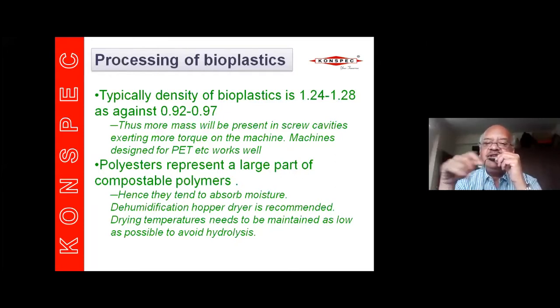At some time we just keep some small leftover material, 2 kg, 5 kg. I just tie it up with a rope and keep it on the one side. I have found that MFI of the material has increased from 3.5 to 120. So it hydrolyzes so fast. So please ensure whenever we are processing that moisture is a very, very critical component of processing, and it has to be kept away from the product.